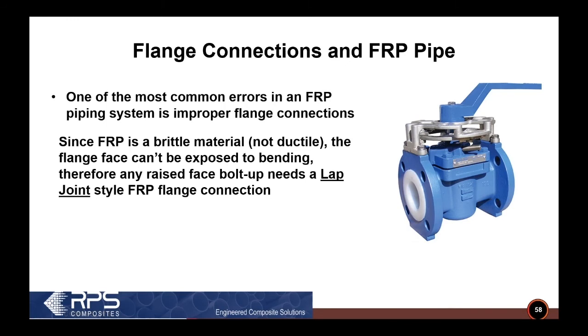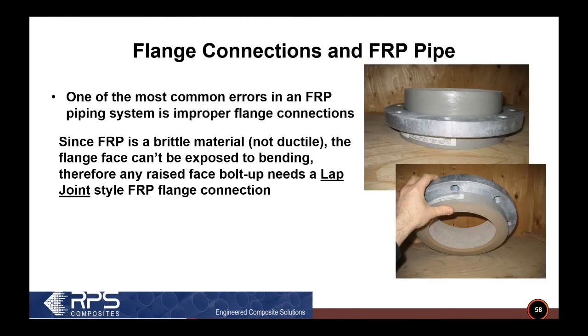So if you use a full face FRP flange that has the bolt holes in it and you crank down on it, it's going to be unsupported out past that rubber lining and is likely going to crack when you torque down on it. So what you need to do is use a lap joint style flange.